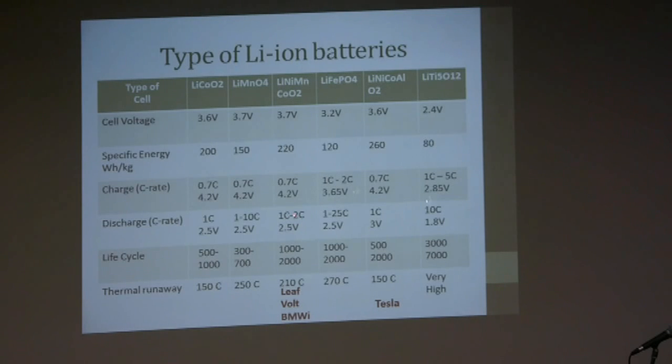Because what does it say? You can actually get 2 times the cell capacity of current out of it. Now, if you have 10 amp hour cells, then that means you can get 20 amps out of them. But then, if you put, say, 100 amp hour cells in there, then that means you can get 200 amps, because that will then be 2C.